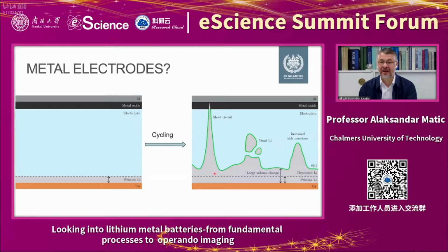So instead of having a dense bulk phase, what we often end up with is a very rough surface, and also a surface which has reacted with the electrolyte, forming a passivation layer, the SEI. But this passivation layer can also isolate part of the metal, causing the formation of so-called dead lithium. In the worst case, we can get protrusions of metal growing through our cell, through the separator, so-called dendrites, in the end causing short circuits.